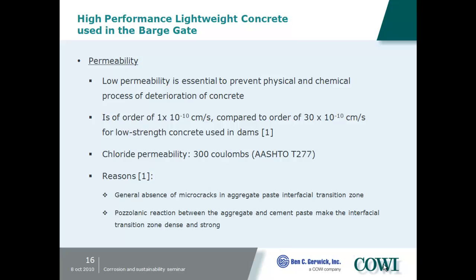And as I said, the permeability can be very low, on the order of 10 to the minus 10 centimeters per second, as compared to something that might be 30 times higher for a normal strength concrete. So in more extreme cases, you can have 100 times or more lower permeability, because the lightweight aggregate is slightly pozzolanic. It will actually bind better to the cement binder, which reduces the permeability. Also, it's harder for bleed water to accumulate under a porous aggregate. So it's a proven fact.